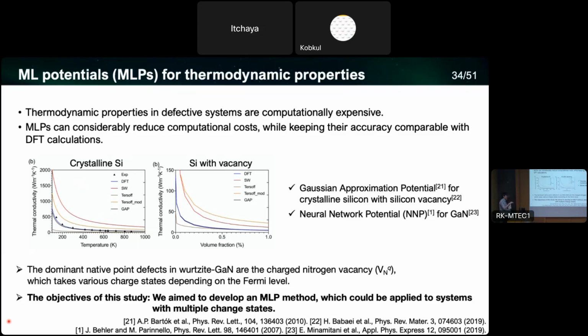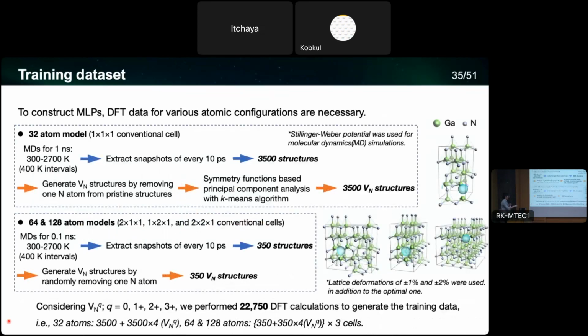changes depending on the Fermi level. Like when the Fermi level is close to the valence band, the most stable one is the +3 nitrogen vacancy, but it transitions to the +1 nitrogen vacancy at some Fermi level. So this difference in the charge state cannot be considered by using conventional machine learning potentials. So we introduced some modification so that we can handle these different multiple charge states. That's what we have done in this study. Again, these are the structure data sets, and we consider the nitrogen vacancy with neutral, +1, +2, +3 charge states. And these are the number of data sets we have prepared.